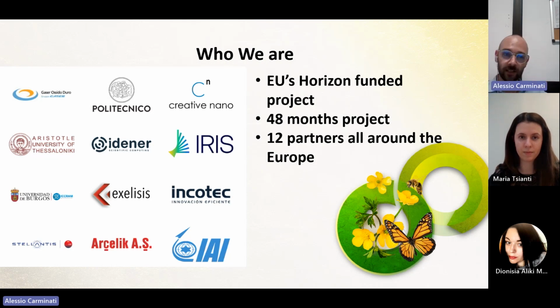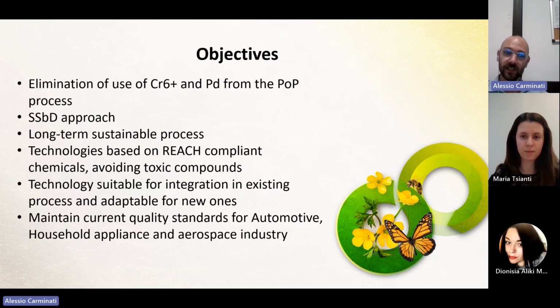So the objective of the FREEME project basically are 2. One is, so the FREEME project involves the nickel plating process of the plastic. And in this kind of process, you typically use 2 different chemicals that the project aims to remove from this kind of industries. So the first one is the chromium 6 etching of the plastic substrate, and the second is the palladium activation of the substrate.